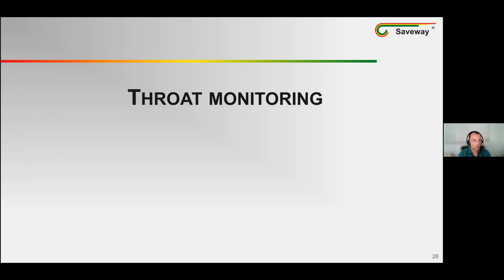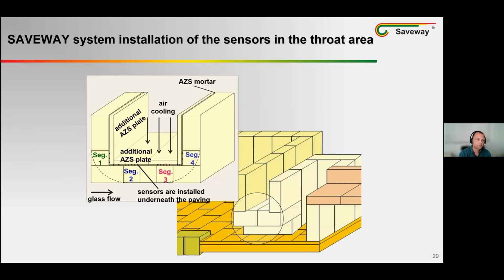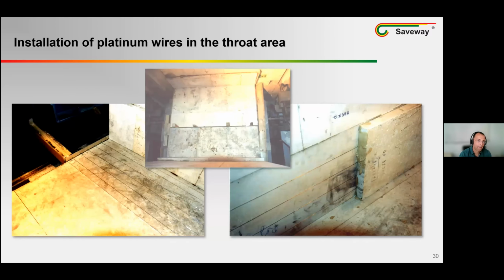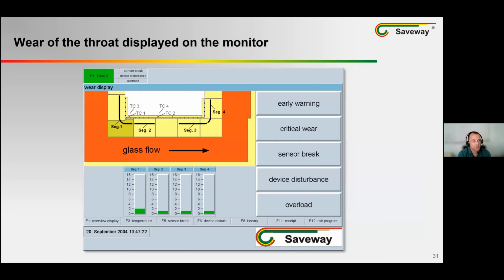Another case is throat monitoring. In this case, we use platinum as the electrode. The particularly critical area is monitored with electrodes behind AZS plates. Sensors are installed underneath the paving. In this example, there are 4 segments to detect the resistance of the furnace lining. They are placed on the left and right side and below.